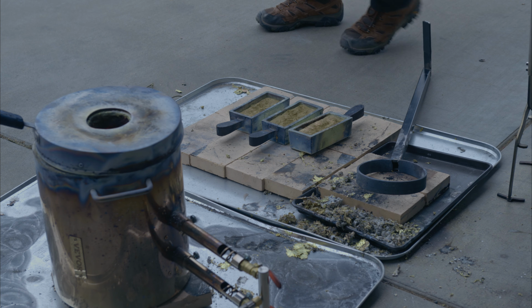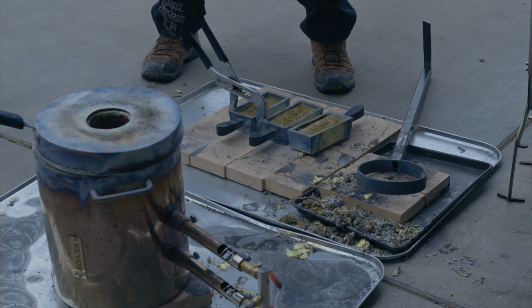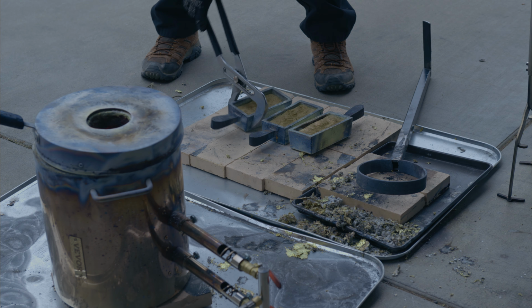Here you can see me removing the ingots from the molds. Normally, you can just flip the mold and the ingot will fall out. If it doesn't, let it cool a little bit more and try again. Sometimes you have to pick them up and sort of drop them, and the ingot will almost always break free.